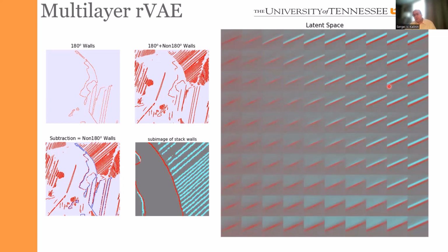So for example, here you can see that ferroelectric and ferroelastic walls basically coincide. So what it tells you is that the ferroelectric wall cannot move without the ferroelastic wall, and vice versa, which means that this is the region where there is strong pinning. So if you're in this part of the latent space, you can see that the ferroelectric wall is more like a straight line, but the color is not uniform. Generally it's bright in the center and weaker at the edges, and there is no visible blue color.